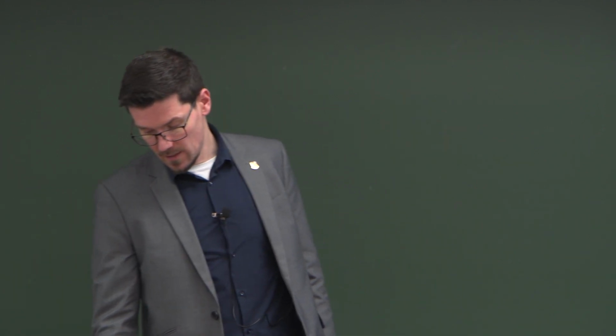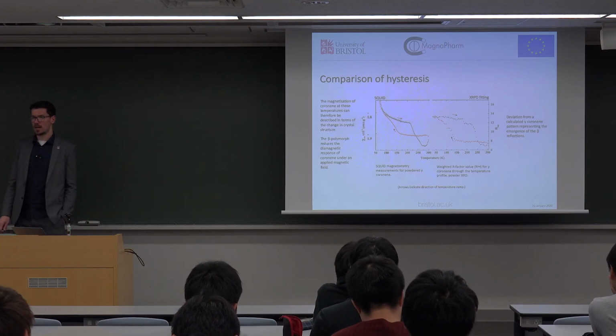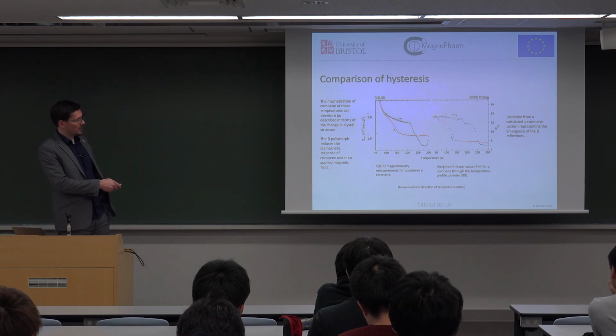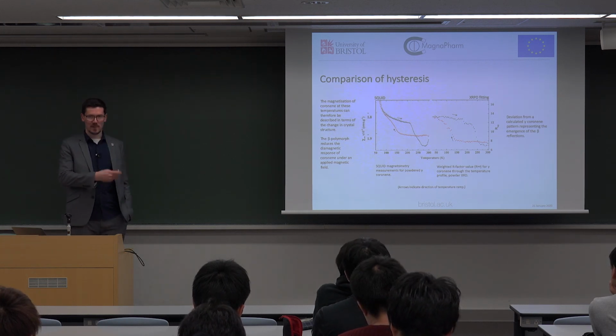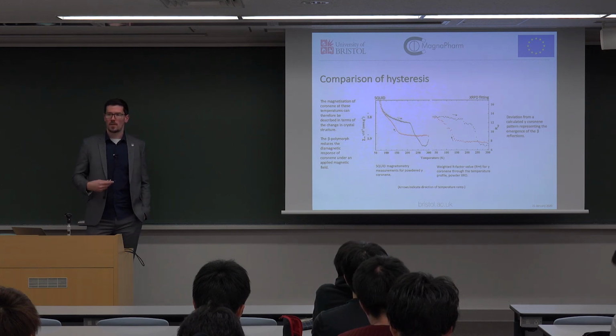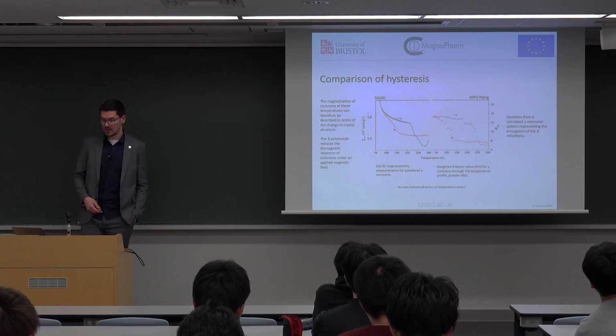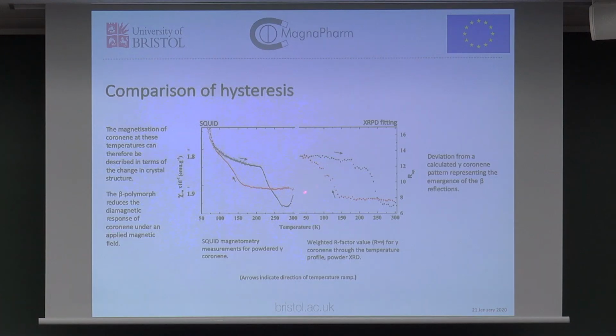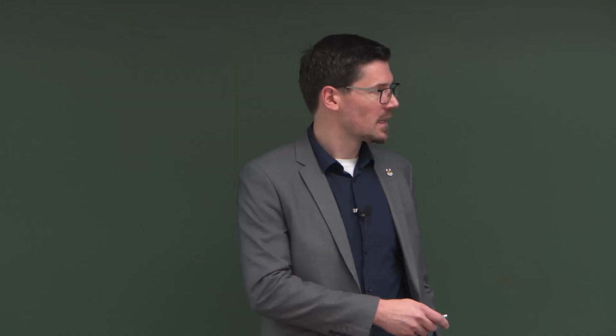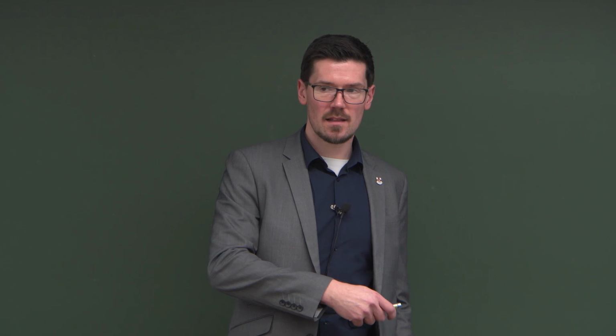So can we see that? In a SQUID magnetometer, yes we can. So I've clipped the data because the paramagnetic upswing is huge and pushes this into the noise. But we've done this many times at different field strengths, and it seems to scale with field strength. So if you follow the red dots back, there's a kind of corner close to 150 Kelvin, and then it swings upwards. And then on the way back down, there's another corner here at about 220 that swings down, and then we end up back where we started when we get to room temperature. So we see a hysteresis in the magnetic susceptibility.